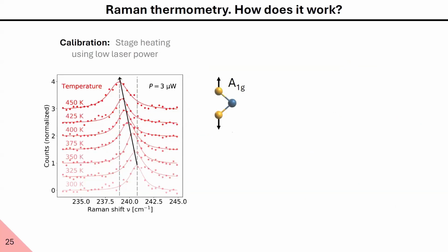So, Raman thermometry. The first thing we need to know is to characterize how our observable shifts with temperature. So basically, we take our suspended region, we shine very low laser power. This is to avoid laser-induced heating effects. And we find out how much shift we produce by a given temperature increase in the sample. This, what we're looking at here, is the frequency of this A1G out-of-plane atomic vibration, which is carrying little heat in